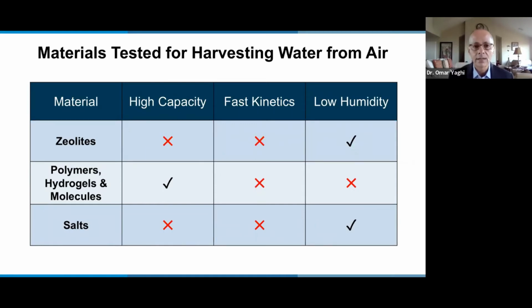And the materials that are being investigated today are shown here: zeolites, polymers, hydrogels, and molecules and salts. And in order for any material to be able to do this and achieve commercialization, they need to have high capacity so that you are not running too many cycles. You need fast kinetics so that water is going in with ease, you take it out with ease without having to apply heat. And you need the material to work at low humidity. As I said, materials that work at low humidity will also work at high humidity, and therefore perhaps we can achieve our vision of harvesting water anywhere at any time of the year. So you can see that these materials, although very attractive, fail in one or more of these categories, making them not so viable in this application.